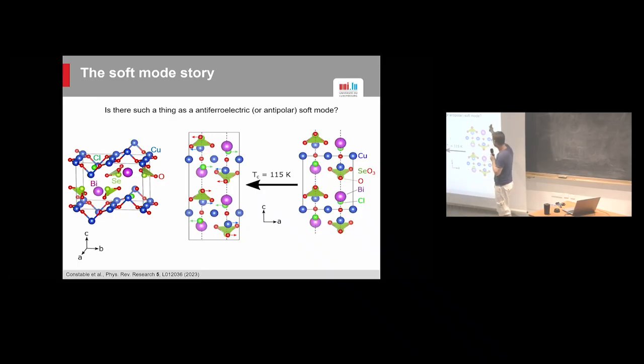This crystal has a terrible chemistry, but it has a very simple phase transition. If you look at it along the B direction, everything is nicely aligned above TC, and when you cross TC, which happens to be 115 K, especially the chlorines, you can just pay attention to those, move in an antipolar fashion, okay? And that's all. There is just a doubling of the unit cell associated to this antipolar motion, but otherwise there is nothing else. There is not even a change in point group, so to relate to what Jirka said during his talk, it's not even a ferroic transition.